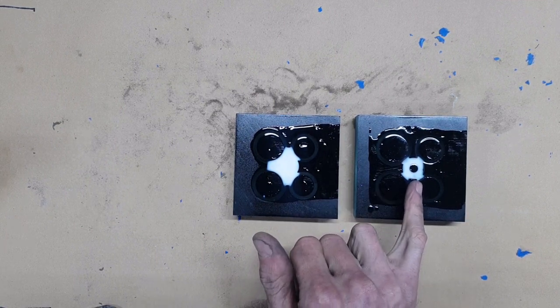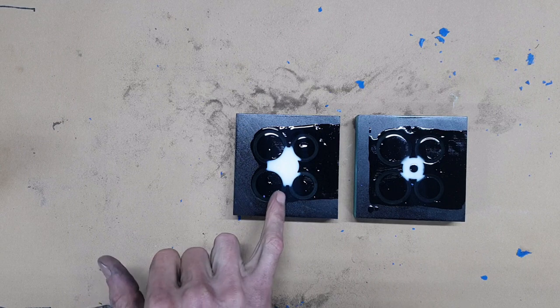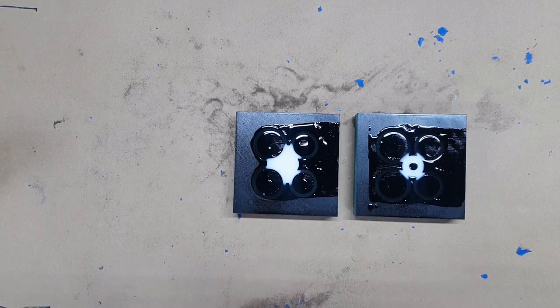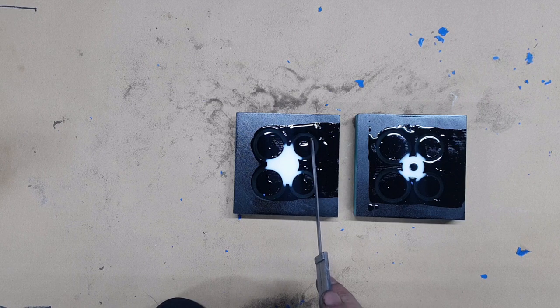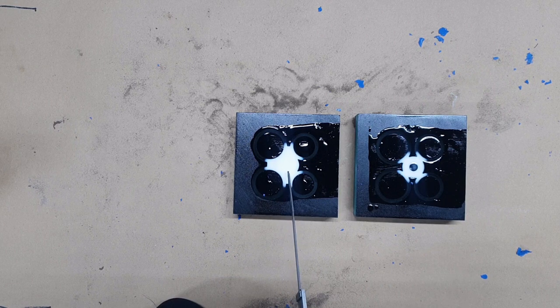You can see there's a vast difference in this one. It's a lot smaller. This one again is still molten here if it was aluminium. So these are all solidified, and this is trying to pull aluminium here. So you would get a tear. Let's just get this out. You would possibly get tears in these areas here where this has gone hard, this has gone hard, this has gone hard, and this has gone hard. So this by now has gone way down in temperature if it was aluminium. These are well solidified, this is still molten. So you can see where the possible issues would be here, here, here, and here, which would let water into the exhaust and intake ports, which you can see if we move to the new method.